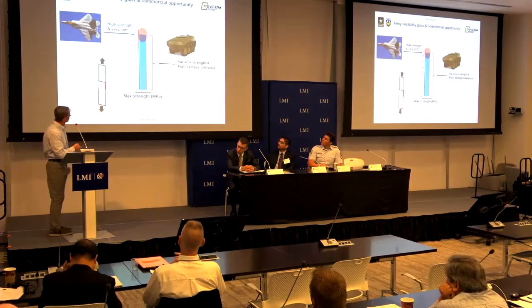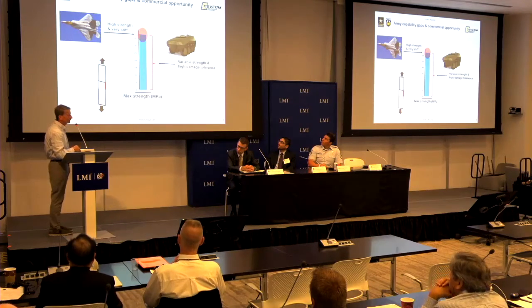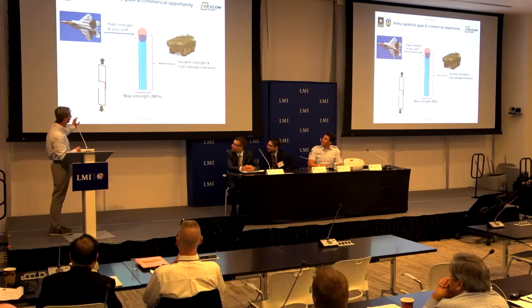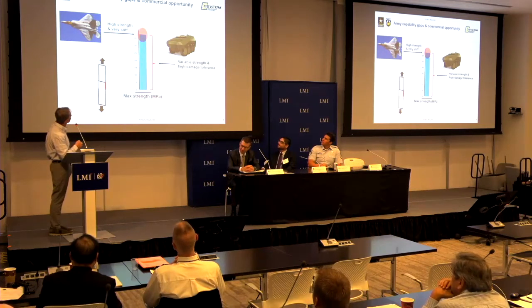And then this is a typical range as you'll see on lap shear strength. My apologies, I nerded out. This is in megapascals. So this is for journal publication, but 35 megapascals, that's about 5,000 pounds per square inch. So aviation's always up here in the upper end of this. It's about 5,000 pounds per square inch, and it's only these adhesives that are used for flight. Whereas armor, we'll see across the whole spectrum, depending on what the armor package is.